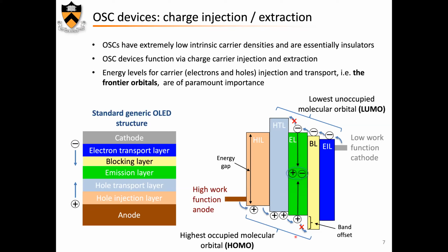And that is depicted here, for example, where these blocks correspond to the valence band maximum and the conduction band minimum, called, for these materials, the highest occupied molecular orbital and lowest unoccupied molecular orbital of different materials put together. And I'll come back to the structure of such a device a bit later. But as you can see, to make this device, which is an organic light emitting diode, function, you have to inject electrons from one side, inject holes from the other side. They recombine somewhere, hopefully in the emissive layer, and produce light.